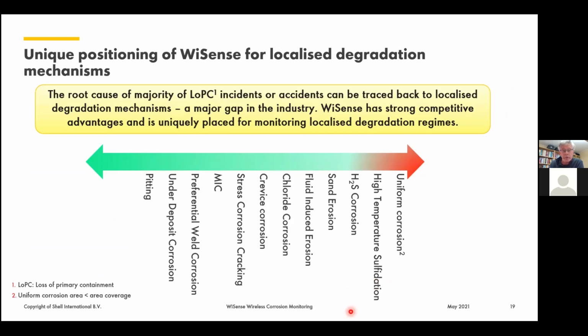Unique position of WiSense for localized degradation. If you look at the mechanisms, then it's only on the right end where ultrasonics is the champion technique, uniform corrosion. You probably know of PermaSense probes, the first wireless monitoring devices in our industry that found a very broad market. Perfectly working on uniform corrosion and extensively used in the refinery where there is high temperature sulfidation, creating very uniform corrosion. But as soon as you go away from that mechanism, then a lot of mechanisms, although sometimes a mix, can become extremely local in the attack of the wall. And I don't need to explain anything about this, but it is the challenge for inspection, but also for monitoring, to get devices that can detect the onset and the growth of such local defects.